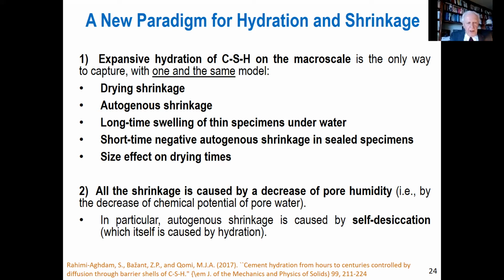Hydration is expansive, and as far as we can see, it is the only way we can capture with one and the same model all these phenomena, especially drying shrinkage, autogenous shrinkage, with the same parameters. Long-term swelling of thin specimen underwater, which can imbibe water. I didn't put long-term swelling or short-term swelling of thick specimens, which are affected only at the beginning. Short-term negative autogenous shrinkage in sealed specimens, which is seen. Size effect on drying times, which is enormous. In my opinion, it is impossible to fit it under the assumption that hydration itself shrinks regardless of humidity. It must be effect of the change of humidity.